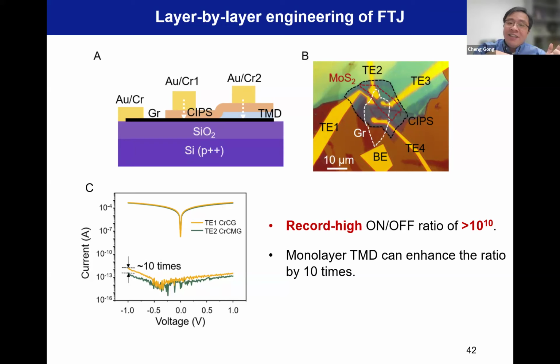At the chromium CIPS interface, you should have some type of Fermi level pinning there, but you don't have the Fermi level pinning on the other side of the interface. So probably because of these three reasons, we get a 10^10 on-off ratio.